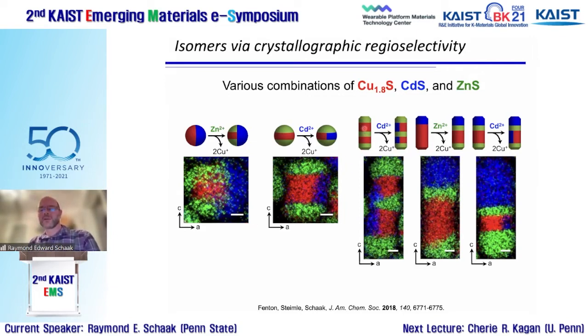For nanorods, a similar thing happens. You can start with these zinc sulfide, copper sulfide striped rods. They do the same kind of thing in terms of caps this direction, and then cadmium sulfide comes in from the side. Or we can start with the cadmium sulfide tip. We can install through cation exchange zinc sulfide stripes and then bring in another cadmium sulfide notch in that direction. So you can start seeing where this is leading, right?